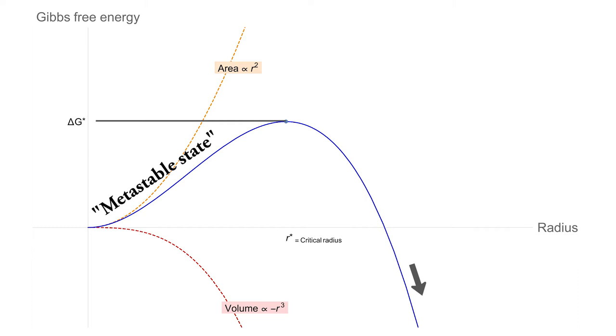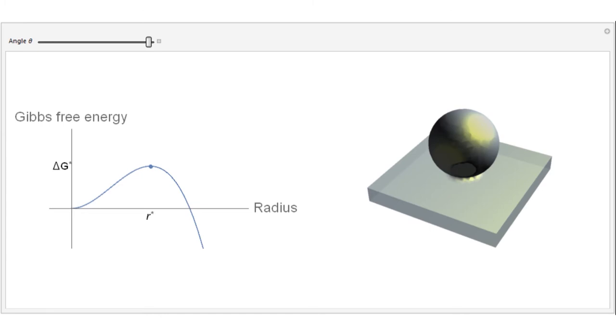We now know that water can start to freeze if by chance the dynamic water molecules in liquid form a crystal bigger than a critical radius r star. This process is called homogeneous nucleation. We'll see the water freeze much faster at timescales that we're used to if we somehow can lower that Gibbs free energy barrier between the forming of water and ice.